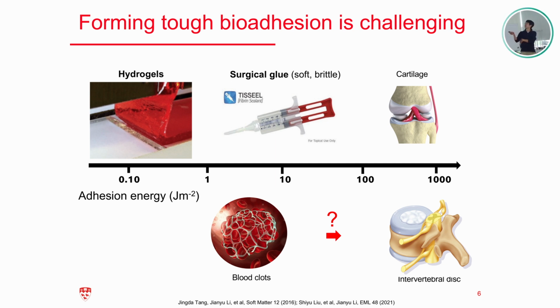So that's why we have measured the adhesion of conventional hydrogels, such as collagen and polyacrylamide, on substrates like skin or glass, and we can find that the adhesion energy, that is a quantity we use to quantify the adhesion performance, is very low. You can see the quantity is on the order of 0.1 to 1 joule per meter square.